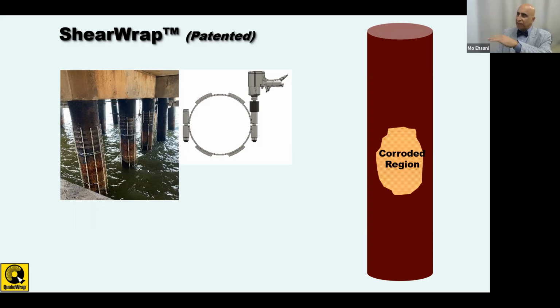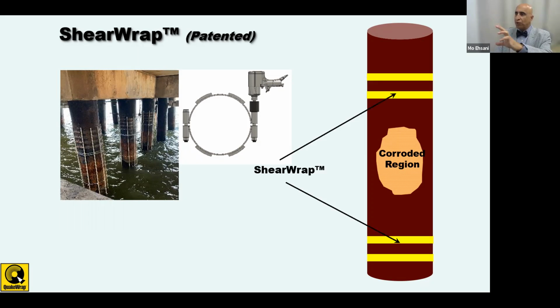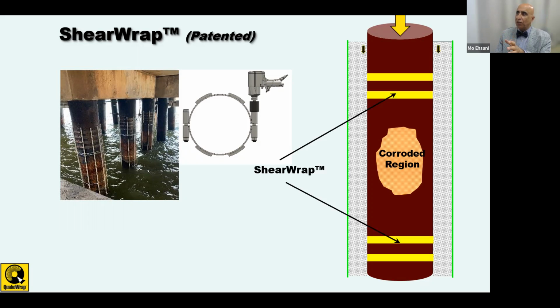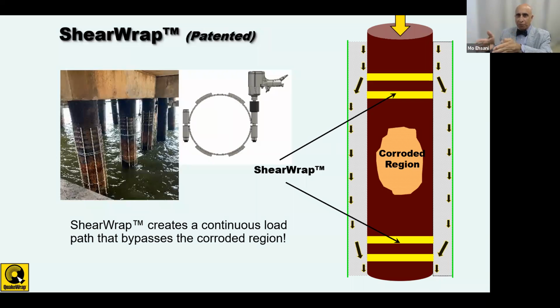For example, if this is a pile with the corroded region shown here, based on our calculations we put 2, 3, or 4 of these shear wraps above and below the damage zone. Then when we put the jacket around it and fill it with concrete, as the load is applied, once it gets to that shear wrap, it transfers into the ring of concrete, bypasses the damage zone, and then goes back down into the good portion of the pile below the region where the repair has stopped. So this provides a continuous load path from the ring of concrete and the original steel structure.